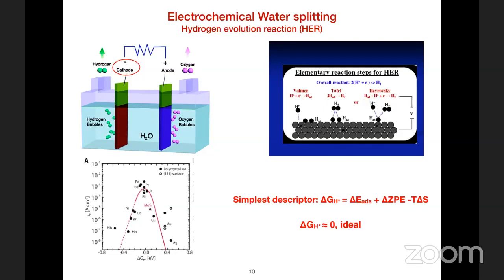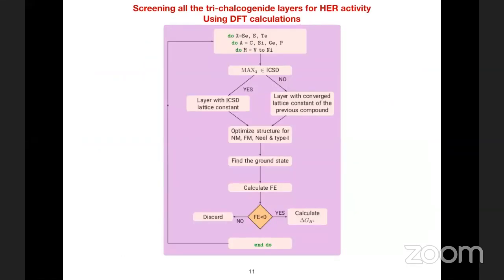And what I would like you to notice from here is that even delta G values close to 0.2 are good in the sense that those metals also show pretty good activity. But platinum is the best. All right, so what do we do here?